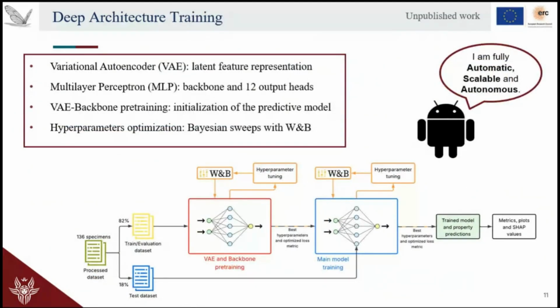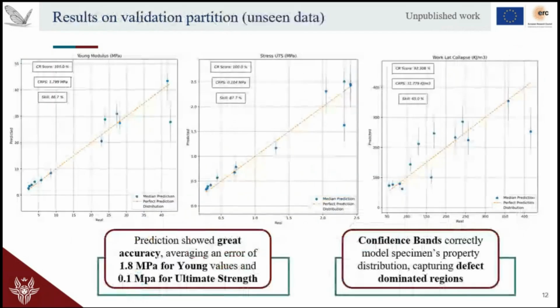So as for training, at first the variational encoder was trained and its hyperparameters were tuned, and secondly the backbone and all the heads were trained and their hyperparameters were tuned. After this training process, the best performing model was retrieved, and it was used for validation on unseen data. And those are the predictions on unseen data, for example, on Young's modulus, the ultimate tensile strength, and energy absorption up to the lattice collapse. And as you can see here, the accuracy is good.